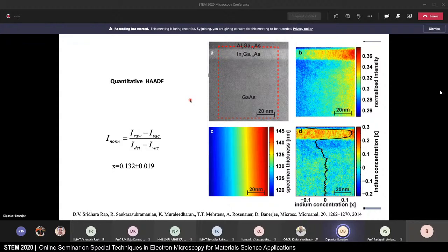It's easy to get qualitative data on composition from high-angle annular dark field because the scattering process is dependent on the atomic weight of the atoms that scatter. So the contrast that you get in HAADF is dependent on composition, but you have to quantify it, and quantification is not a simple matter. You have to do a variety of calibrations of the imaging system. You have to do simulations of the scattering process, and you have the experimental data and intensities, and you combine all of this to get at a quantitative map of composition in these samples.